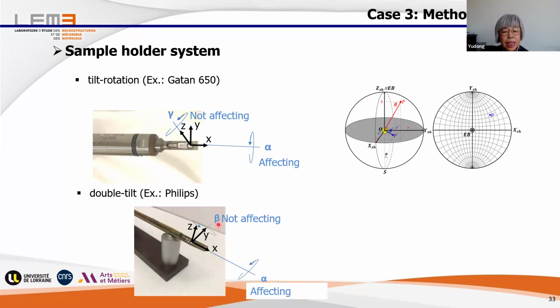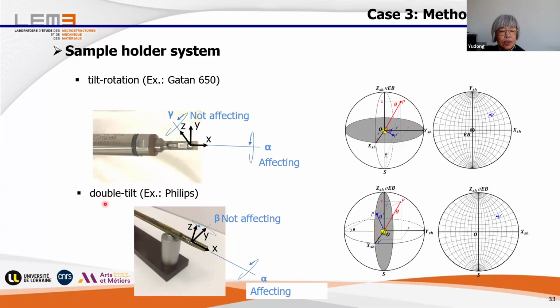And the second type of double tilt holder is alpha, beta. The alpha tilt is always there. And in this case, the beta tilt is around the y-axis. For TEM sample holders, the tilts are specific. For either gamma tilt or beta tilt, when we rotate the sample, the other coordinate axes, either z, x, or in this case y, will not be affected. But once we rotate around the x-axis, the whole stage turns. And in this case, it will affect the other axes. So we have to be careful. For the second case, we select the projection plane like this.